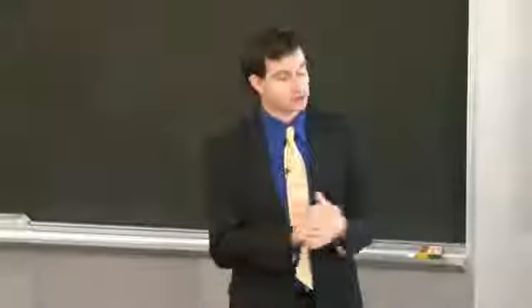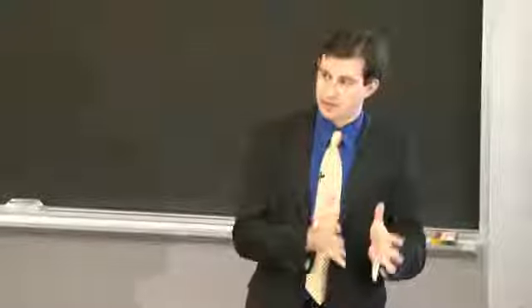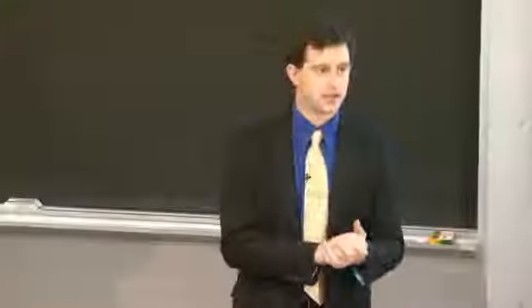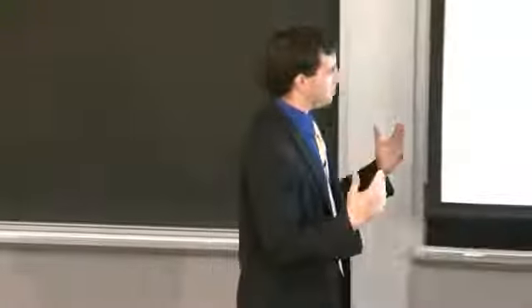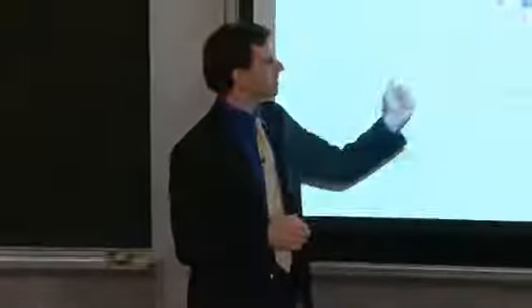Furthermore, that oxide layer, from an electrical point of view, is very passivating. As we solved in the exam, those interface states, or surface states, at the surface of a semiconductor can be reduced or minimized by the presence of certain passivating layers. And it just so happens that, by the benevolence of nature, the silicon oxide, shown in these red triangles right here, has a very low surface recombination velocity, passivates the surface very well, and results in high-performing